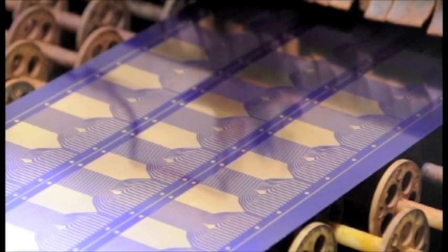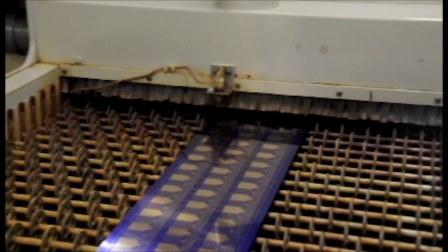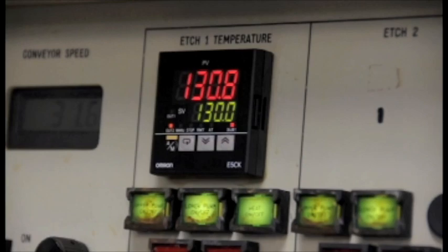Once developed, the work goes into the etching process, where exposed metal will be dissolved in acid, while the resist protects and defines the desired part. Acid strength is regulated by monitoring and adjusting the acid's conductivity and oxidation reduction potential. Moreover, controlling the acid temperature and spray pressure leaves only the conveyor's speed to fix the metal's dwell time in the machine and ensure a consistent result.